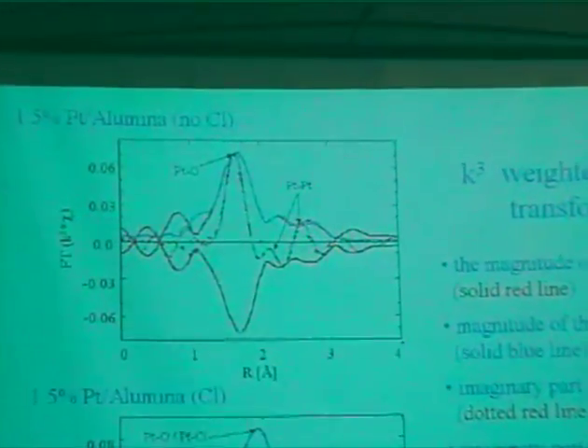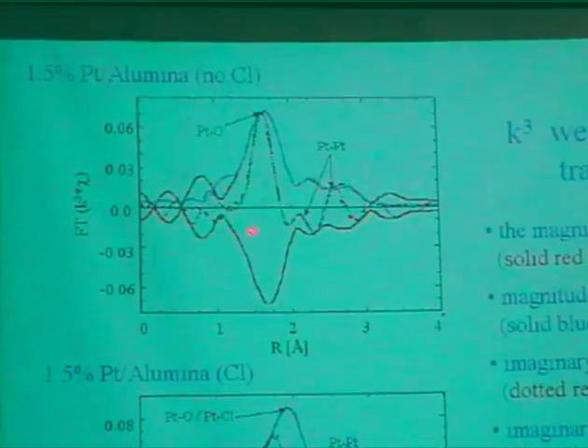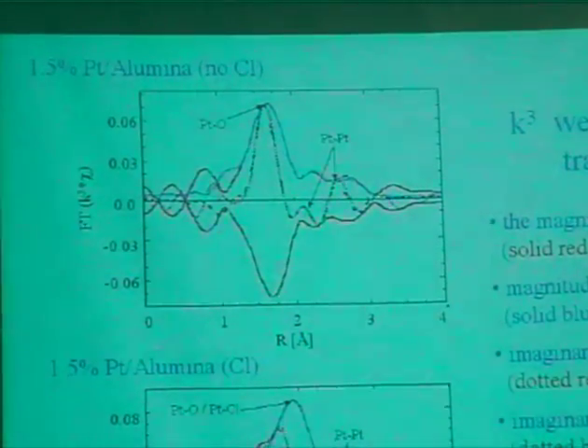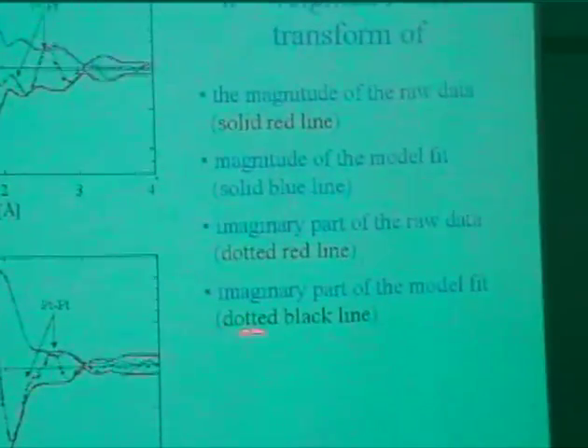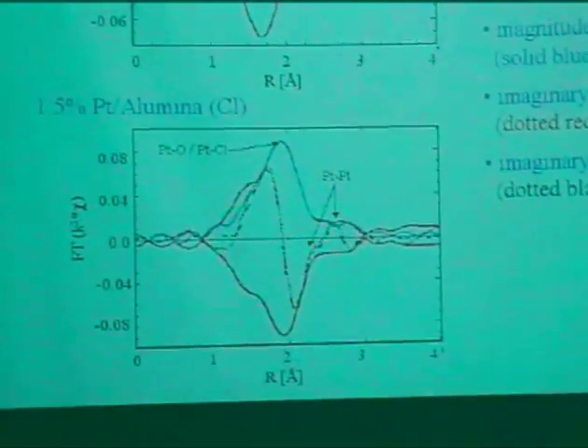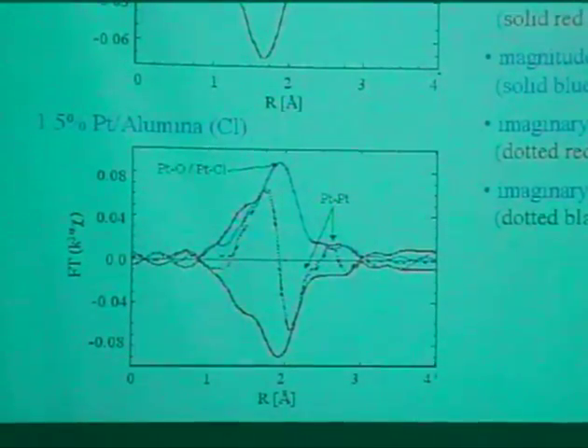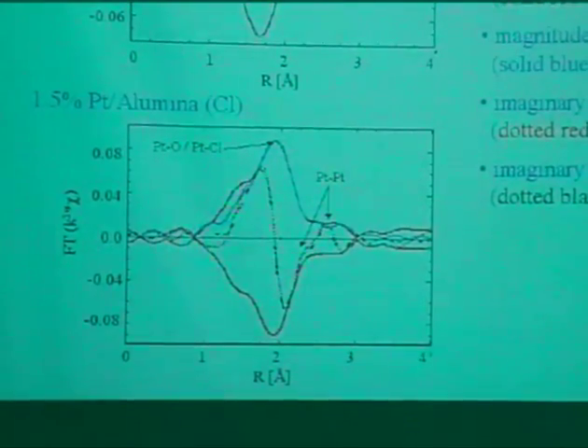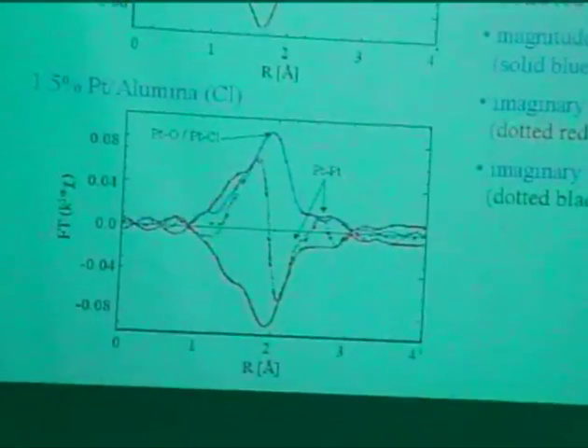We're fitting basically mostly this part, discarding that part. The imaginary part of the raw data is the dotted line, and the imaginary part of the model fit is the dotted black line. And the model fit will tell you what are the scattering distances as well as the number of nearest neighbors. Okay, we are guided by the activity data. So now we have a very nice fit.